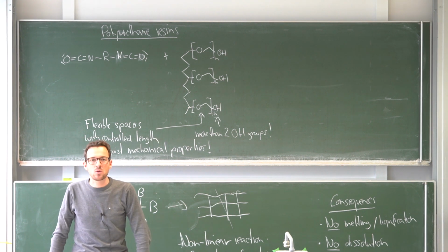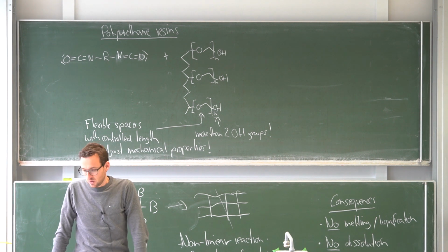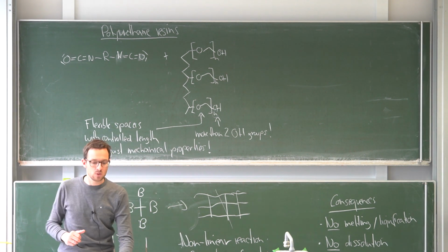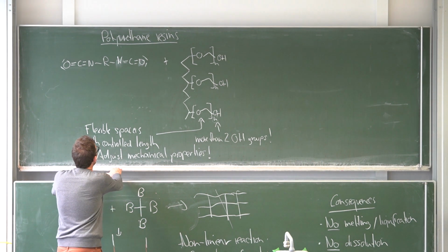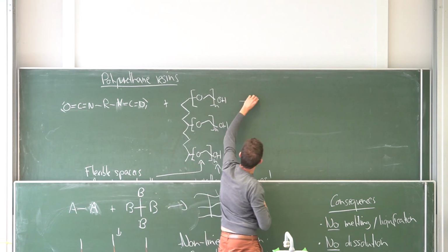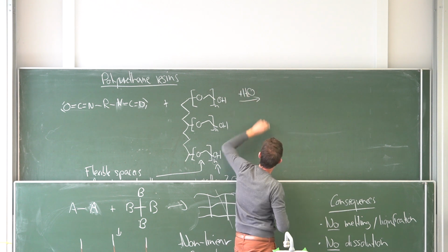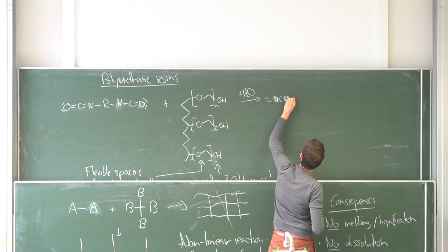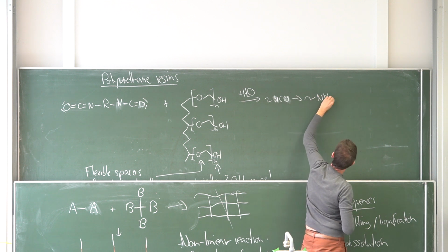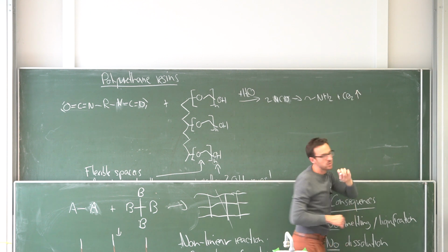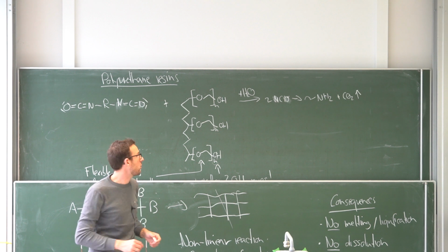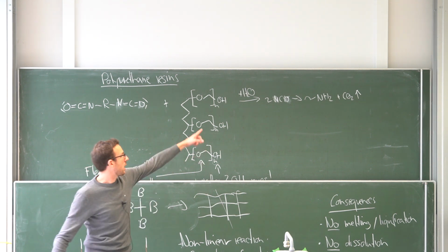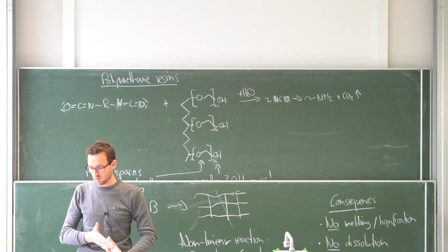So this would be a material that you use to paint your garden furniture, for example, to make it very stiff. If we want to make a foam, as in the mattress or the helmet, we need to imply this possibility to generate CO2 if we add water. So if we add here plus H2O, the OCN NCO will react to NH2, and this will produce the foam, so the whole thing foams up. If we work in a water-free environment, we don't get this, we don't get any foam, we get a continuous coating, for example. I'm not going to do the chemistry again, this is something we did last week, so we can pretty much leave it like this.